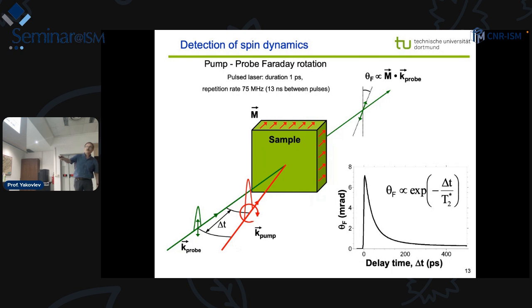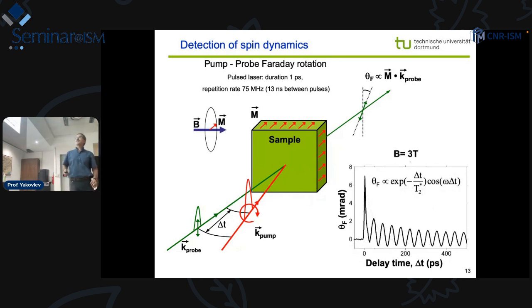Typically, the pump pulse comes here, and then one can observe the decay of the polarization in time. This is without magnetic field. If we switch on the magnetic field, then the picture becomes different, because the spin, with a perpendicular magnetic field applied, starts to rotate about the magnetic field, and the signal precesses. So actually, this is the Larmor precession of the spin.